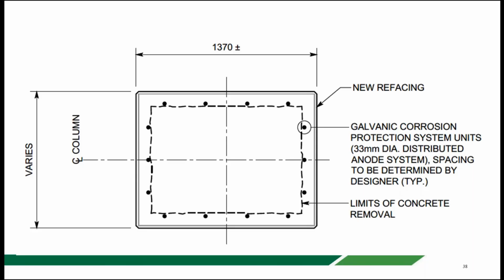And so this image is from one of the bid documents for the job. And basically what it's showing is a section through one of the columns. And essentially, the work involves removing the existing concrete cover down to the depth of the top layer of reinforcing steel that's here, shown by the dotted line. They are not chipping behind all of that steel unless the concrete is already spalled or delaminated, in which case they are. But generally they are not, because, at least from what I understand, the structure is remaining in service during this work, and they want to maintain the confinement of the concrete core.